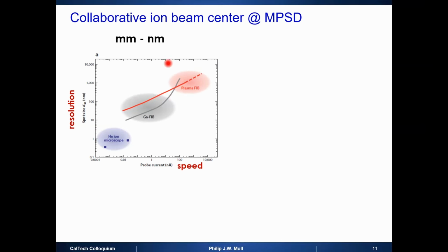What has been very successful is the development of plasma FIBs. These are mostly xenon-based technologies, but we're operating multi-gas species systems. So we can use xenon, argon, oxygen, and nitrogen, which helps with energy matching. These are technologies for very large structures, in the millimeter to micron range. And then there's also the helium ion microscope, which you also have available here. That allows you to have ultra high brightness beams in the sub-nanometer range.